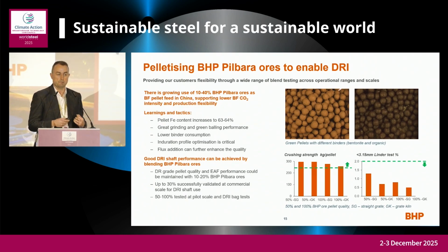Pilbara iron ores are easy to grind, particularly with dry grinding compared to other iron ores, and have good balling characteristics. Generally lower binder consumptions. In terms of the optimization, we've got to really work hard on the induration temperature profile and the fluxing and which blend partners. And we haven't fully worked that out yet, but we're having success going from 10 to 20%, which we believe you could probably maintain a reasonable EAF production, blending our iron ores into the pellet.